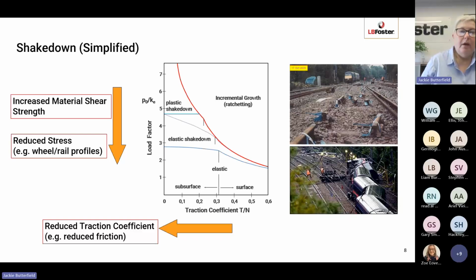Another way of predicting whether you will get rolling contact fatigue is to use a shakedown diagram. Now, this is a diagram which on the x-axis you have the traction coefficient, so effectively the friction involved in that particular wheel-rail interface, and then up the y-axis you have a load factor. So this is a ratio between P0, which is the peak pressure, so this is the maximum pressure experienced on the rail during wheel-rail interaction, divided by a material strength factor, Ke. So what you're looking at here is different areas of reaction of the steel to the friction and the loading.